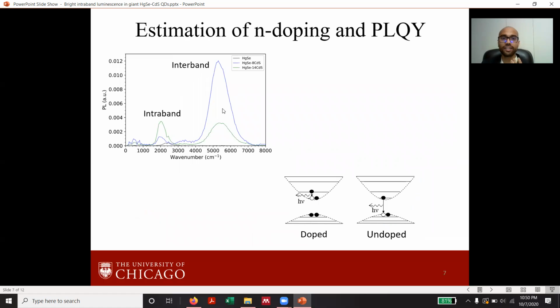This is how a typical infrared fluorescence spectrum looks for the mercury selenide CdS quantum dots. The peak at 2000 inverse centimeters is the intraband luminescence from the fraction of the dots which are n-doped, and the peak at 5500 is the interband luminescence from the dots which are not doped. Just by looking at this spectrum, we cannot calculate the fluorescence quantum yield since we do not know the doping fraction, and the quantum yield for the intraband and interband emissions would be different.